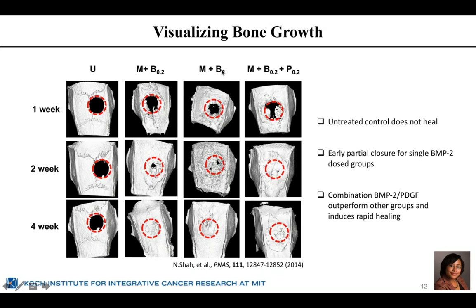If we increase the dose to 2 micrograms, we also see regeneration. These are actually considerably low doses. The typical dose that is used in the collagen sponge product I described is on the range of 3 or 4 milligrams as opposed to micrograms. Now, we also see that if we introduce BMP2 at 0.2 micrograms and the platelet-derived growth factor, 0.2 micrograms, that combination film gives us a somewhat faster healing, and that we can see here.